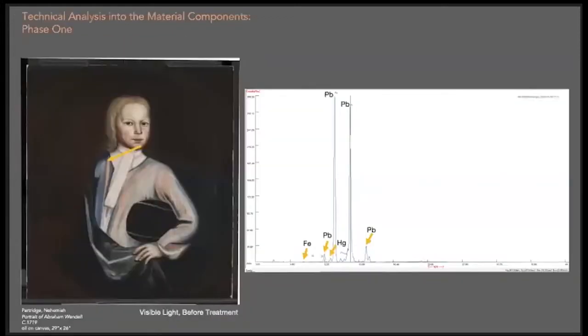Initial analysis included handheld X-ray fluorescence spectroscopy. This technique involves the use of a handheld X-ray fluorescence spectrometer that irradiates a point of the painting with high energy X-rays in order to determine the material's elemental components. While light elements below sodium are unreliably identified or detected with the XRF, heavier elements such as lead can easily be detected. XRF is able to penetrate through some surface materials like grime, dirt, and varnish in order to get a better understanding of the composition of the layers beneath the surface.